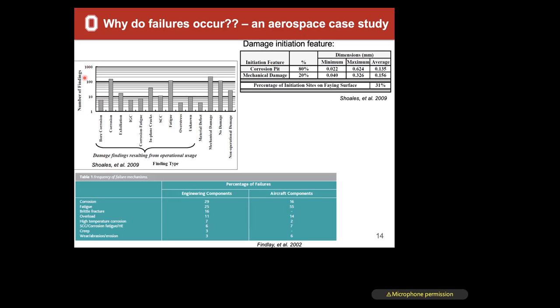And so you can see number of findings based on the type of damage, and there's also, this part had no damage. And you can see there's things like mechanical damage or material defects. So mechanical damage might be, a rock hit the plane and caused a scratch or a dent or something. You can also get mechanical damage when you rivet something on and the person doing it misses and the drill bit hits something. So there's mechanical damage, but the majority of damage sites they found are related to what they call operational usage, and a lot of them related to corrosion. So you can see pit corrosion, regular corrosion, exfoliation corrosion, that's that flaking up I showed you, intergranular. You can see corrosion fatigue, stress corrosion cracking. These two are environment-assisted cracking related. You also can see fatigue here, and in a second I'll comment on that.